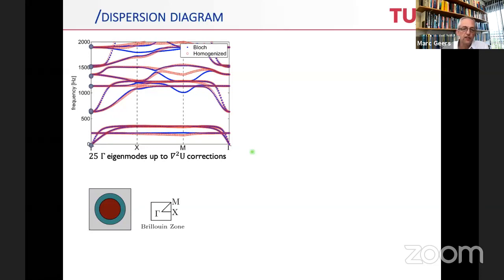If we take 25 eigenmodes at the gamma points and we use grad 2 corrections, this is typically what we would find. So here we compare with the Bloch solution, which is actually the full solution of the problem. And that allows us to compare how our effective continuum is doing. By the way, the Bloch solution can only be used for infinite media, whereas the homogenized solution just tells me what the continuum does and could be used also for finite structures. So 25 gives a fairly good response close to the points I've taken.